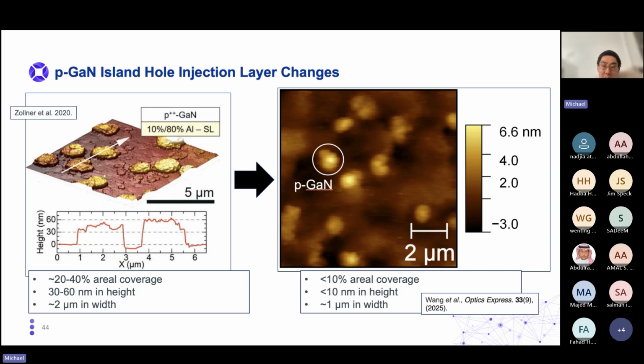So as you recall earlier on, when I showed the stress, the compositional gradients, and the stress going from compression into tension, with this thinner n-type aluminum gallium nitride, it doesn't have as much time to go into tension. So the top of the material is at a different stress state, which results in different p-type gallium nitride morphologies.